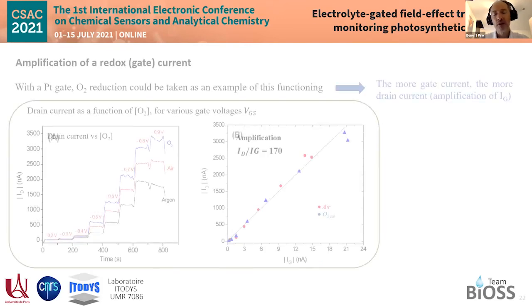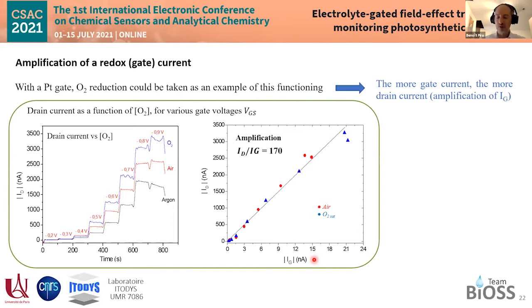What is interesting here is that we could use the platinum gate as a catalytic electrode, catalytic gate, and, for example, monitor the electroreduction of oxygen, dissolved oxygen in the electrolyte, by putting the gate at a convenient potential. Negative potential here, because we use a p-type semiconductor, so the transistor works in p-type and then in the negative quarter of the gate. Here is just to show you that, depending, of course, on the gate voltage, change here in red, in electrolyte without oxygen, then with some oxygen, and in blue with saturated oxygen,